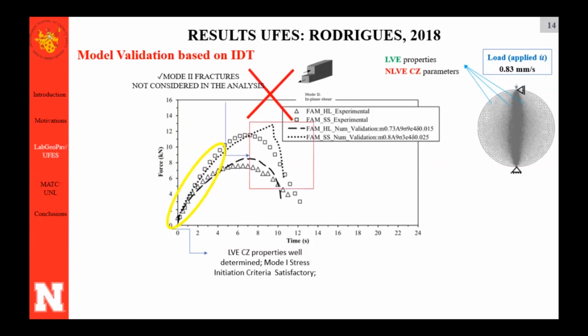But we didn't have a very good match in the post-peak, after the peak load. So this may be due to some mode 2 fracture that happened, because when we do a calibration, we calibrate mode 1 parameters, but we still need to find mode 2 parameters. And we didn't consider that the test that we use, the IDT, is different from the SCB with a notch, which is considered pure mode 1. IDT may also have some mode 2 cracks being developed, and maybe if you calibrate or find a way also to get mode 2 parameters, we can get a better match after we have several cracks being developed.